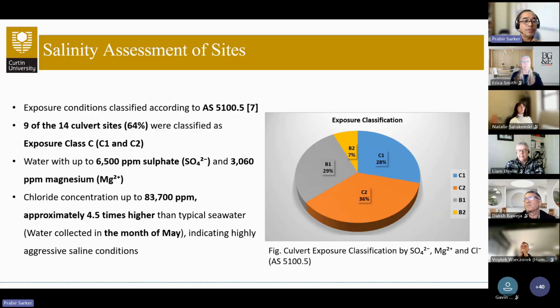Water with up to 6,500 ppm sulfate and over 3,000 ppm magnesium was found. Chloride concentration was very high, up to 83,700 ppm, approximately 4.5 times the chloride content of seawater. So in some of the sites there were very aggressive conditions in terms of sulfate, magnesium, and chloride content.